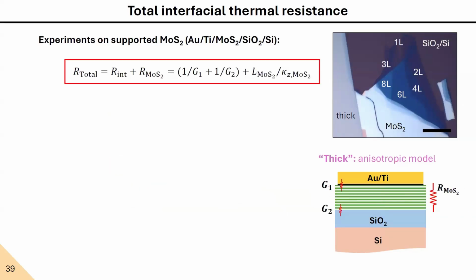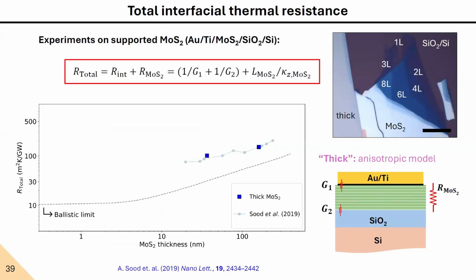Let's first convert these results into an effective total resistance, so a thermal resistance provided by transport across the interface, the flake and the interface towards the substrate. So how do they compare with literature? For the thick flakes, we get pretty good agreement with the available literature values, and basically the difference between our experiments with these available experiments is the use of a different transducer material. They use aluminum and we are using gold, and still we get similar numbers.